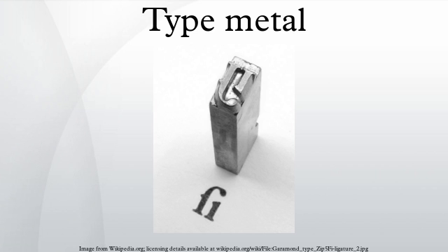Dross equals regeneration metal. Regeneration metal was melted into the crucible to replace lost tin and antimony through the dross. Every time type metal is remelted, tin and antimony oxidize. These oxides form on the surface of the crucible and must be removed. After stirring the molten metal, grey powder forms on the surface, the dross, needing to be skimmed. Dross contains recoverable amounts of tin and antimony. Dross must be processed at specialized companies, in order to extract the pure metals in conditions that would prevent environmental pollution and remain economically feasible.